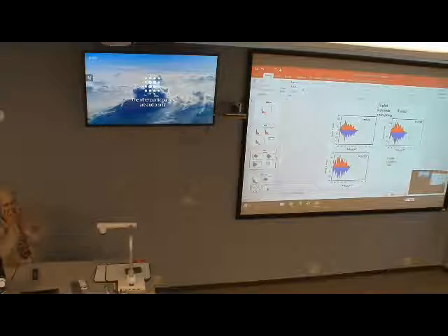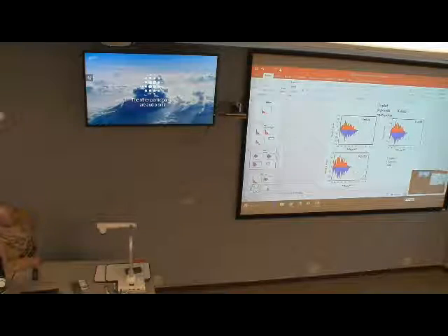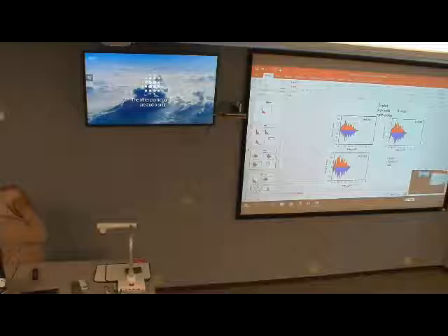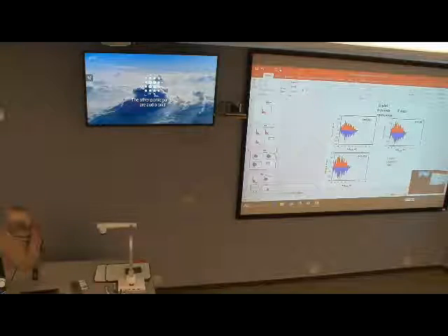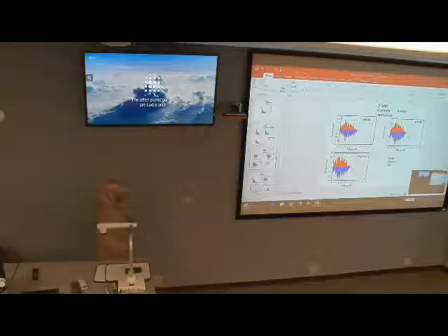Probably, Fatima, you are anticipating that since it is a periodic structure in the z direction, there will be additional effects on optical properties due to momentum distribution, and you just try to systematically include it in the calculation. So, for the second part of the question, most likely the transitions without change of k vector at the gamma point will contribute most to emission. It is expected, but for a systematic consideration, additional transitions are planned to be included.